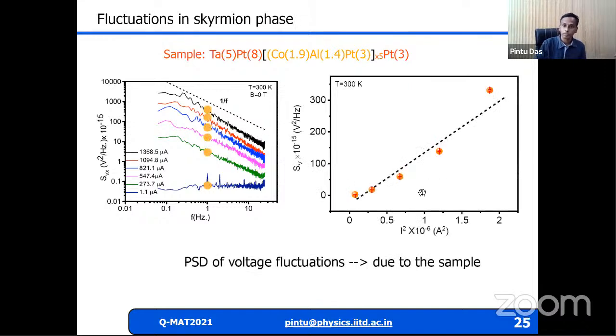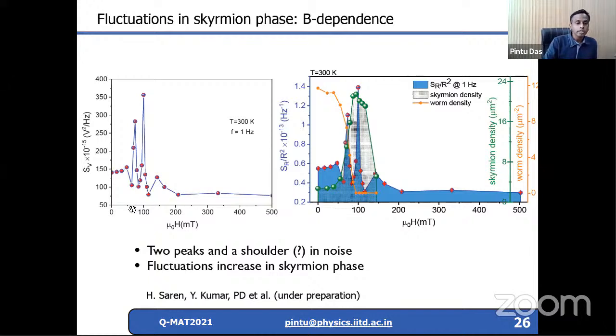So it is indeed a quadratic dependence on the current. It shows that this noise is due to the sample and not due to any extrinsic effect. So now what we did is we performed these measurements as a function of field in the entire field range, the interesting field range, I would say. And then what we are plotting here is the power spectral density at 1 hertz as a function of field. If we plot that, we see that there are two peaks appearing in the region where the skyrmions are appearing in the system.